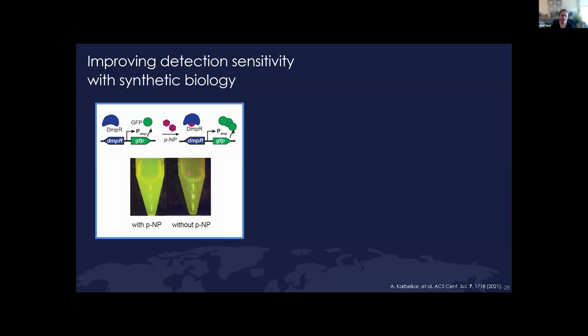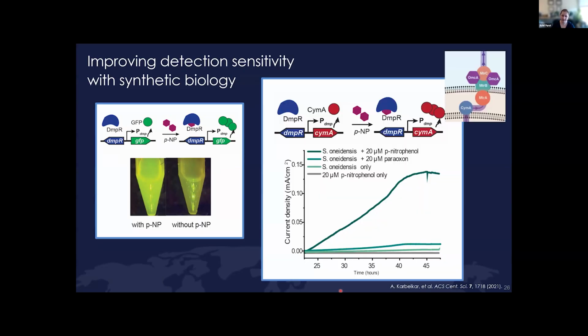The challenge here is even without this p-nitrophenol, we still see green fluorescence because of leaky or nonspecific expression. And so that's unfortunately not going to be a viable sensor, because we won't know if our on signal is due to a low concentration of that molecule or because of this kind of background expression. So what we did instead was to put this DmpR protein to control this protein CymA. And CymA is from a microbe called Shewanella oneidensis, which was originally isolated from pond scum in upstate New York.